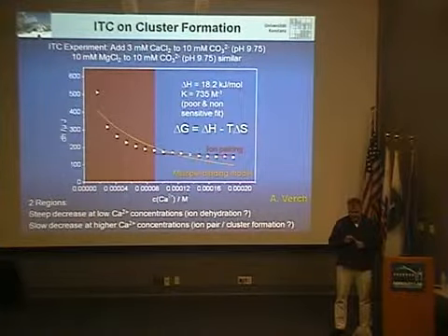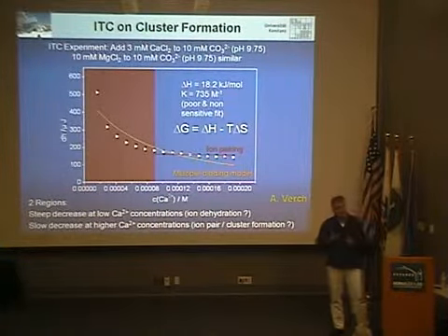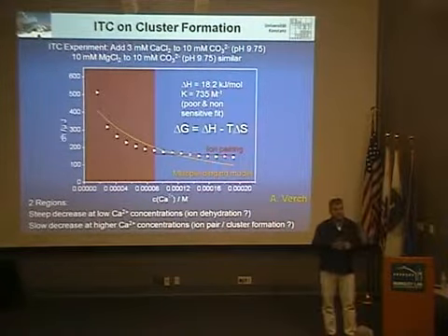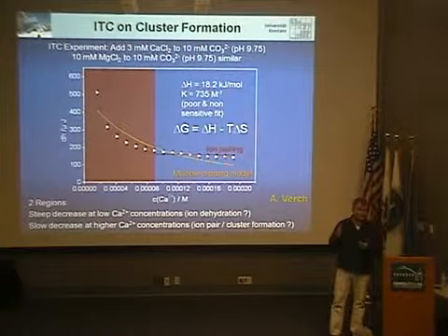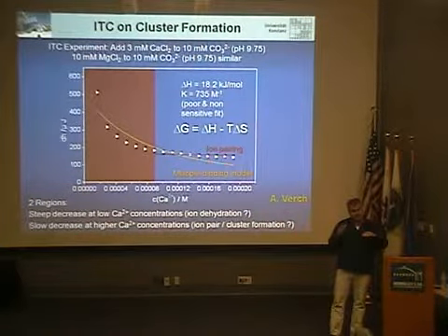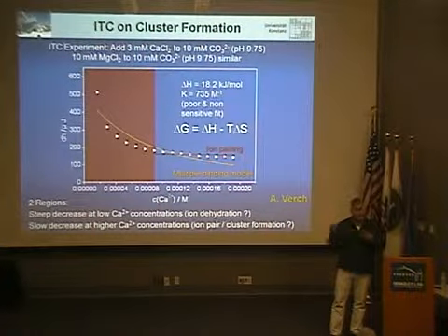So far, the experiments indicate that the silica must at least be outside, or some of the silica, because if you raise the pH to 11.4, which is only slightly higher than 11, you get them stable and you can isolate them, whereas at pH 11, they are still aggregating.